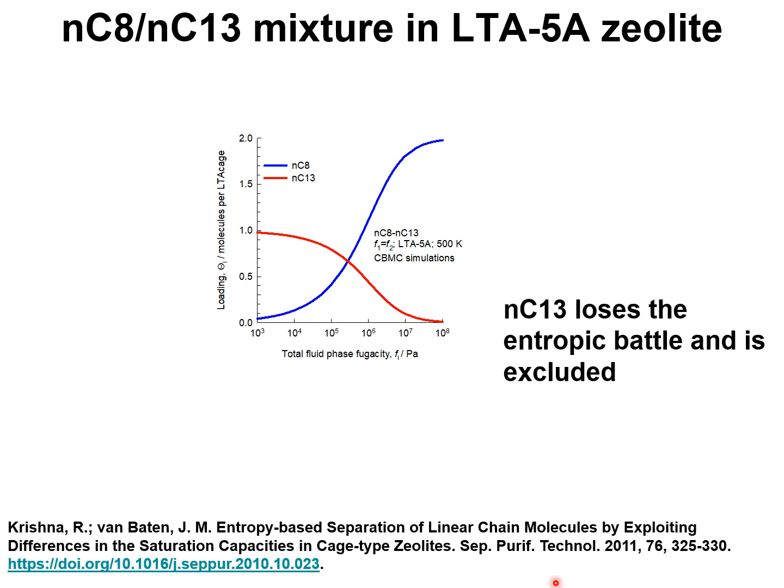However, due to the limited capacity of a single cage of LTA-5A zeolite that has an effective diameter of 11 angstrom, the concept of adsorptive dewaxing is limited to alkanes with a chain length of about NC13, NC14, and NC15.